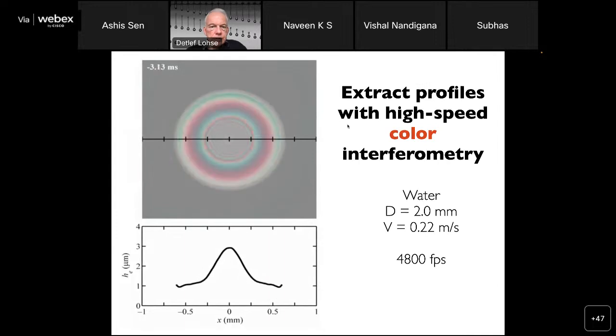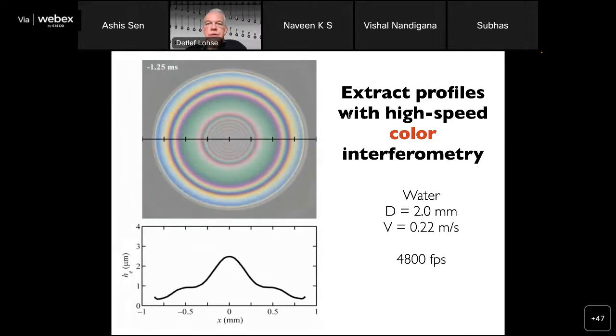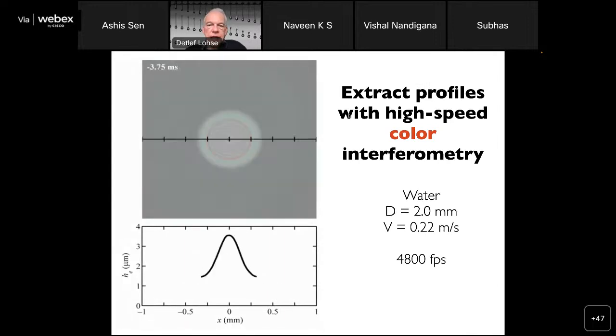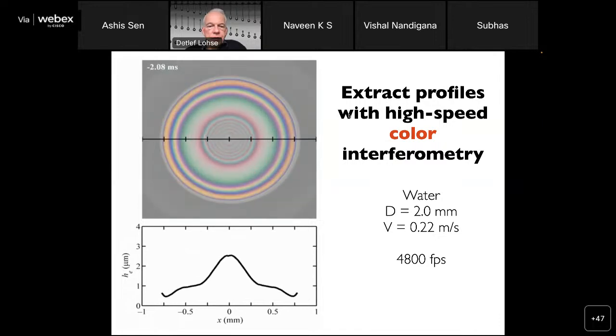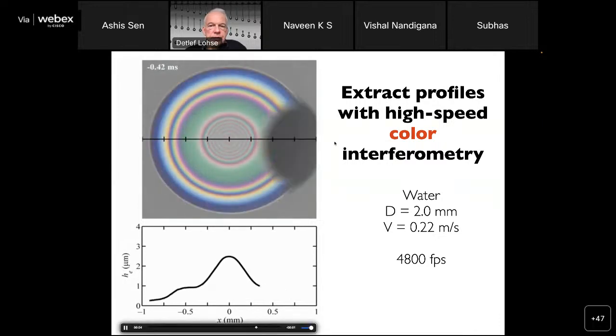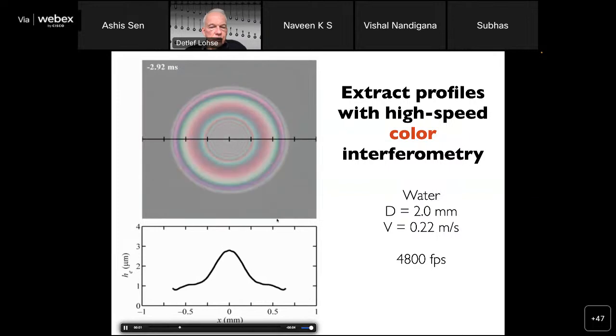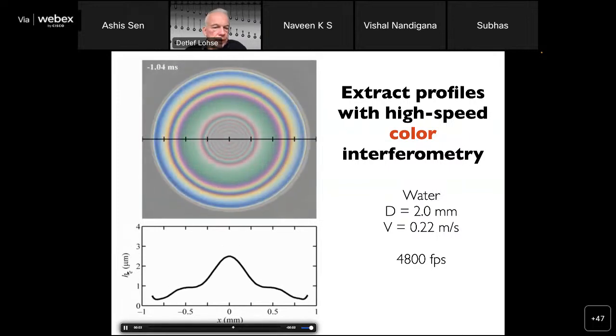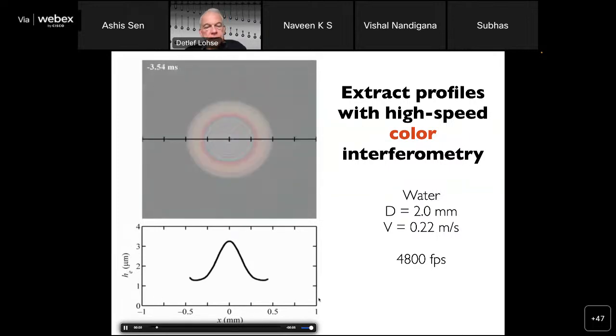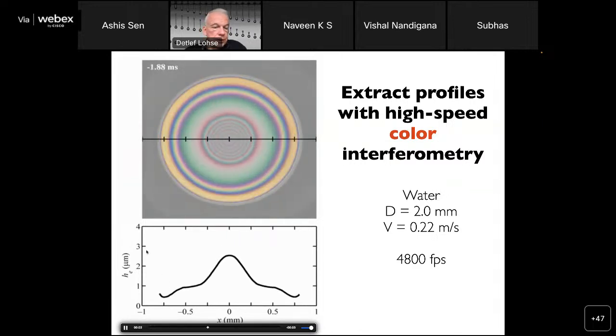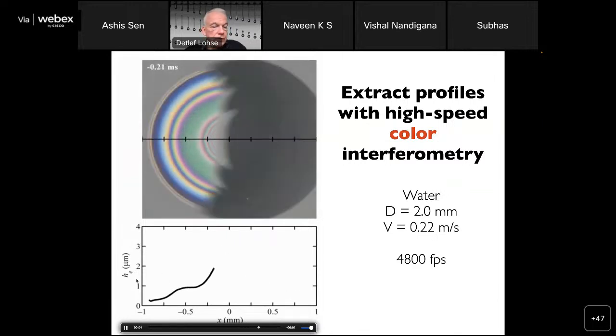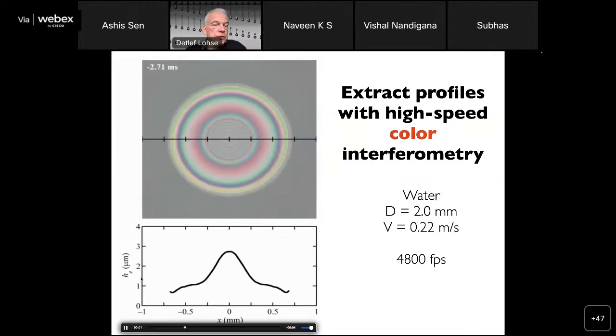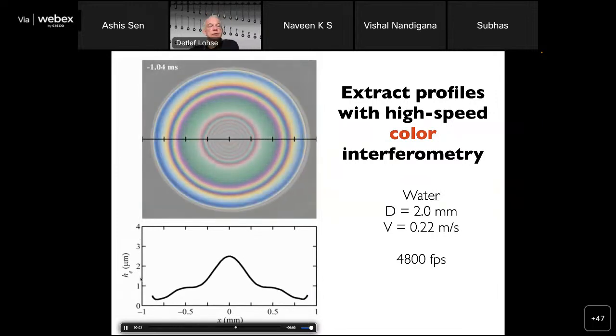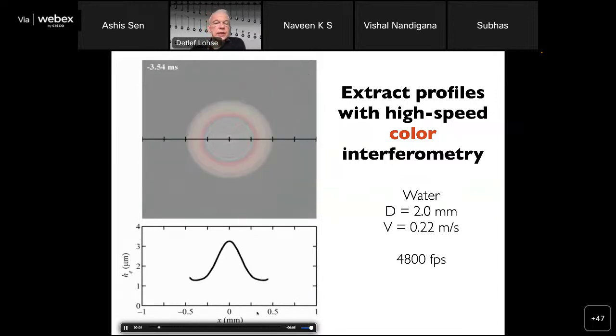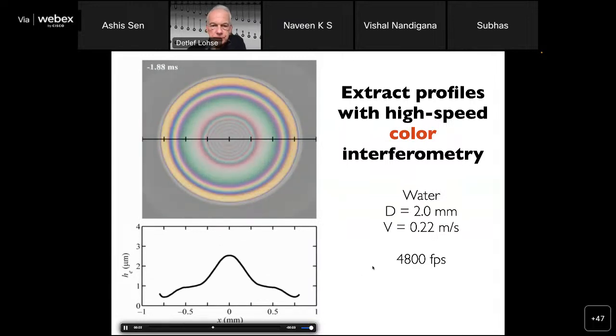So here, in fact, you see how we do this. We do this, in fact, with high-speed color interferometry, which is very, very good to extract the profile. So here you see the profile H in micrometer and the lateral scale in millimeter. I mean, note that this is strongly deformed, so there's a factor of 1,000 in the scale as compared to the scale here at the bottom.